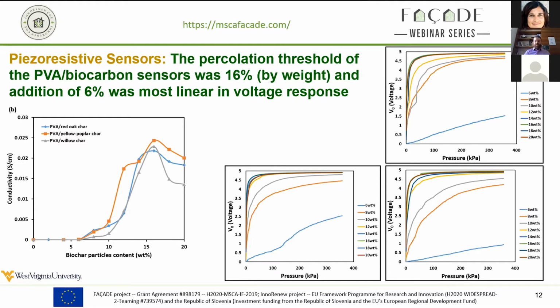So if you're using these sensors in, say, a robot hand to be doing some kind of automated repairs to a satellite, for instance, which is some work that we've looked at in the past, you might be putting too much pressure on a part and actually crushing it. So it's important to get the right type of carbon in there and the right weight percentage. And then the one on the left is just showing that you get to a certain point, in this case 16%, where you don't gain any more conductivity in this type of composite. It actually gets a little bit worse.